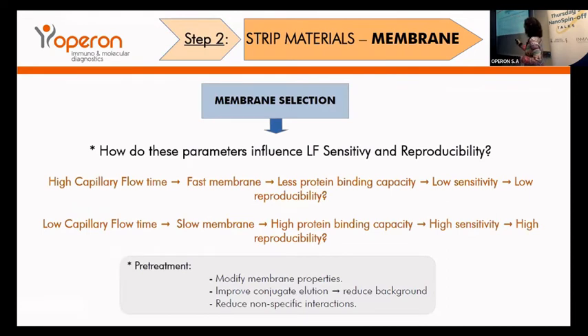And finally, the aim is to select a membrane depending on our requirements regarding sensitivity and reproducibility. So, how do these parameters influence these two issues? Well, high capillary flow time means a fast membrane and less protein binding capacity. Therefore, we will have tests with low sensitivity and usually low reproducibility. On the contrary, low capillary flow time means a slow membrane, high protein binding capacity, and therefore the development of high sensitivity and usually high reproducibility.